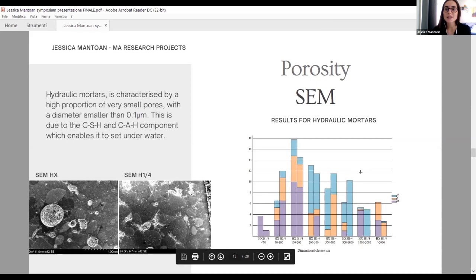The other important change in hydraulic mortar that we can see in relation to the use of barium hydroxide is the change in porosity in the group of pores between 300 and 2000, which are the sorption pores, and they are the pores that are usually used by the material to transport liquid water. That is really interesting because those pores are directly correlated with the permeability of the mortar, and usually hydraulic mortars have a really low porosity. In this case, we can start to believe that mortar containing barium hydroxide probably has a better permeability with respect to traditional mortar.